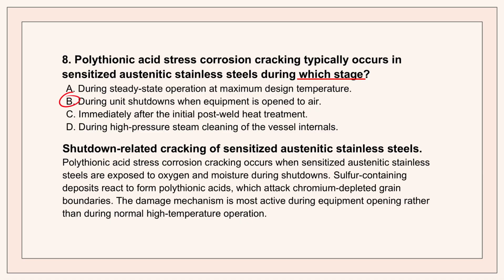This failure affects what we call sensitized austenitic stainless steels. Basically steel that's been damaged by high heat exposure, which depletes the chromium at the grain boundaries. So the material is already vulnerable, but why does the failure wait until the unit stops? Sulfur compounds build up on the surface during operation, but it's only when that sulfur-containing scale reacts with oxygen and moisture from the air during the shutdown that these highly corrosive polythionic acids are formed.